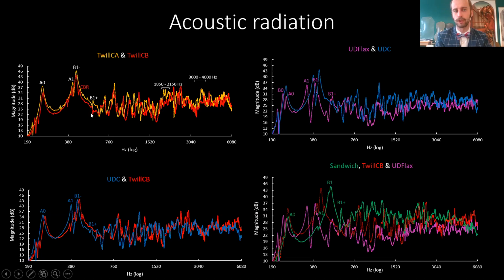This is due to, we found through modal analysis, a lot stiffer sides. Because we use carbon fiber in the sides and they end up going through the back plate, it is very, very stiff. And therefore, apparently, it affects the radiation of the B1 plus mode. So we found that to be the case. If we compare TwillCB with the unidirectional carbon, you see that the modes shift down a little bit. So as you make the plate more anisotropic, the frequencies go down.